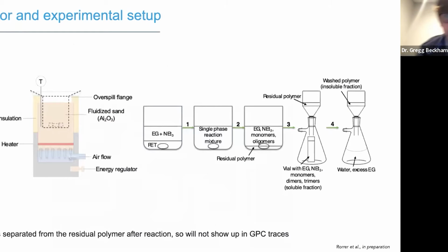Here's our reactor and our experimental setup. This is extremely simple. All of the kinetics data I'm going to show you were simply collected in these Swagelok union type reactors. Basically, you take ethylene glycol, triethylamine, and PET, and at reaction temperature this essentially becomes a single phase. After the reaction, you have monomers and oligomers left if you go to high conversion extents. You can then filter out hot to recover your excess ethylene glycol, and then recover monomers, dimers, and trimers when you filter this hot.